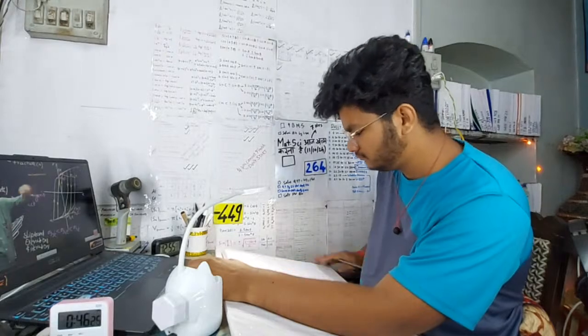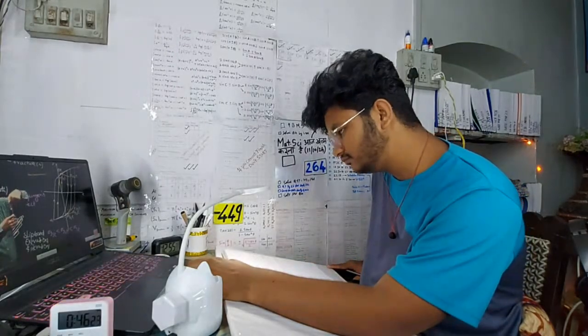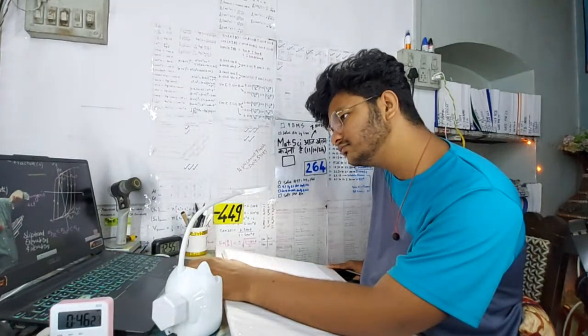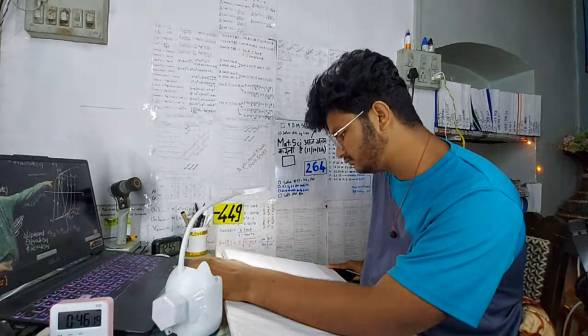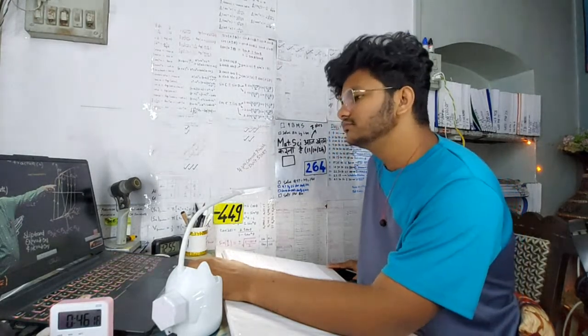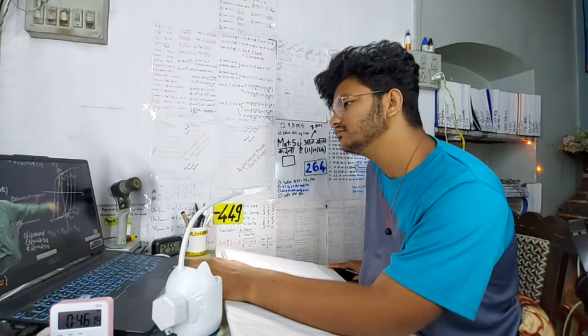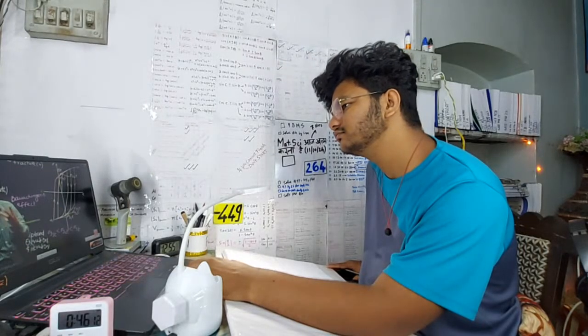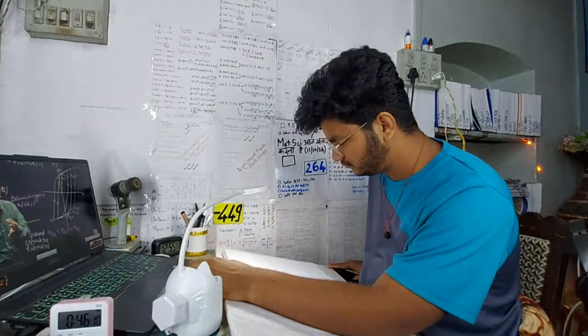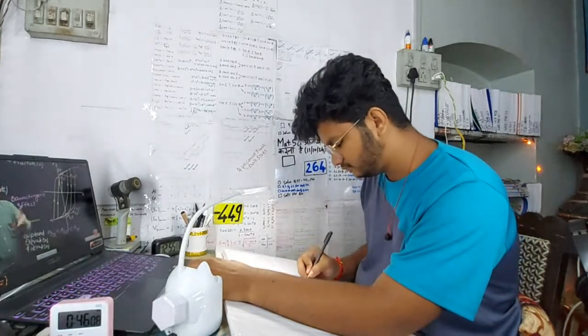Number 2, opposite type of edge dislocations will attract each other and decrease the number of dislocations, hence the strength of the material decreases. In cyclic loading, the yield stress of the material decreases cycle by cycle. These are all the reasons for premature failure of materials subjected to fatigue loading.